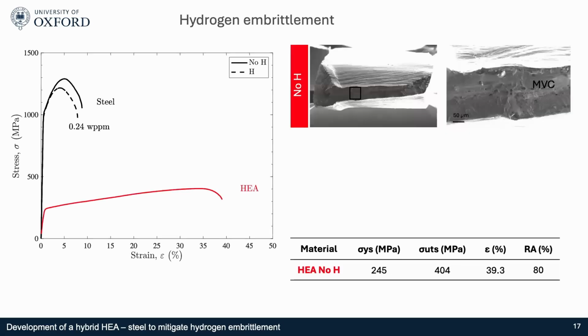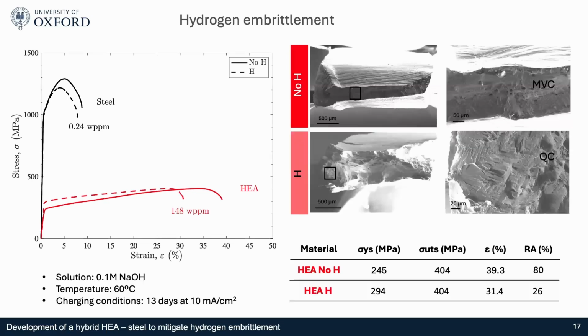Then for the high entropy alloy, after introducing hydrogen for 13 days, we saw a hardening effect. Here, the yield strength was increased, but the elongation was reduced, as well as the reduction in area. So we can say that the high entropy alloy suffers a little bit of embrittlement. Looking at the fracture surfaces, with no hydrogen there were some voids, and for the hydrogen one we saw quasi-cleavage. That was the result after introducing 150 ppm of hydrogen.